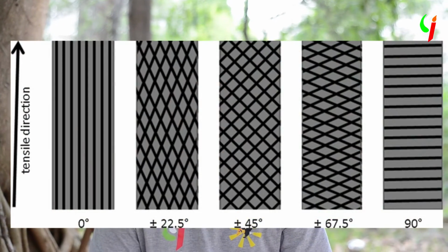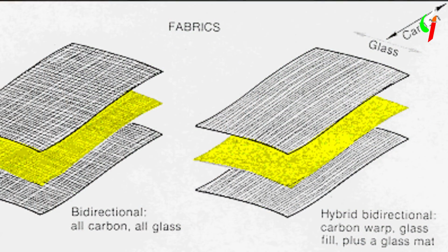The later part of the 20th century saw the emergence of so-called advanced fibers. Fiber reinforced composites have been prominent over any other forms of composite because of one simple reason. Most composites are stiffer and stronger in their fibrous form rather than any other form. The reinforcement effect in the fiber's axis is very high. We get little to no reinforcement in the transverse direction. But we can rearrange the fibers in 2 dimensions or 3 dimensions to get the proper reinforcement. But this does not take away the fact that we won't get high reinforcement in directions other than the fiber's axis.